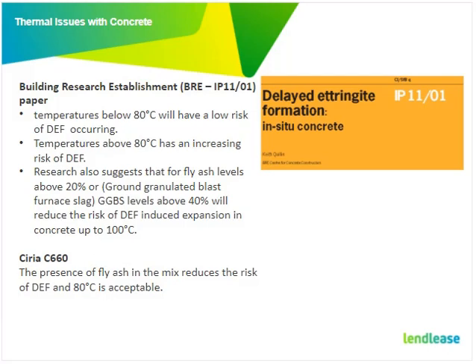If you look at the notable two pieces of research or standards on delayed ettringite formation, in the UK there's the Building Research Establishment paper. They basically documented that any temperatures below 80 degrees will have a low risk of delayed ettringite formation occurring. As you go over 80 degrees, it has an increasing risk, but there's also research that suggests that if you've got additives such as fly ash levels above 20% or slag levels above 40%, then you can reduce DEF up to temperatures of 100 degrees.